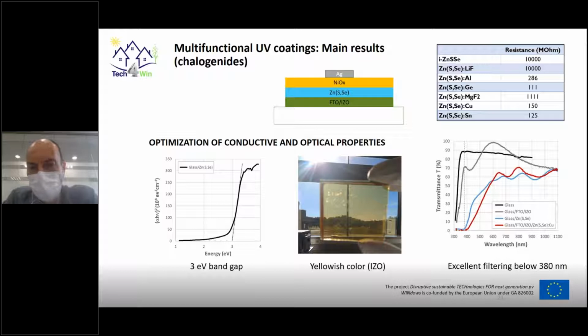We have seen that this has a problem: it determines a yellowish color, and you can see it in the photographic image in the slide. So we know that we need to solve this problem of the yellowish color, and for this, we will replace the IZO by a nickel oxide layer, for example. But we have seen that we can control the band gap very well by controlling the sulfur to selenium ratio. In this case, it corresponds to a layer with a 3 electron volt band gap.